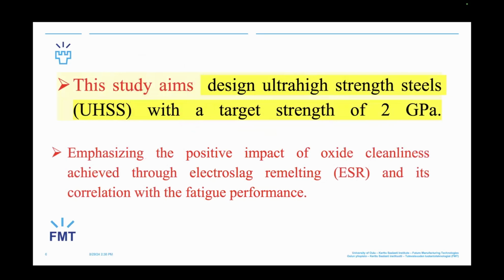Now our study is mainly to design ultra high strength steel with a target strength of 2 gigapascal, and also to study the positive impact of oxide cleanliness, because this steel was melted and cast in Egypt. But now our friend studied for a PhD in Finland, and he got this material in Finland and did processing in Finland, but he didn't do electroslag remelting to clean the steel from non-metallic inclusions. So now we want to study the effect or impact of cleanliness on our steel and the fatigue behavior of the steel.